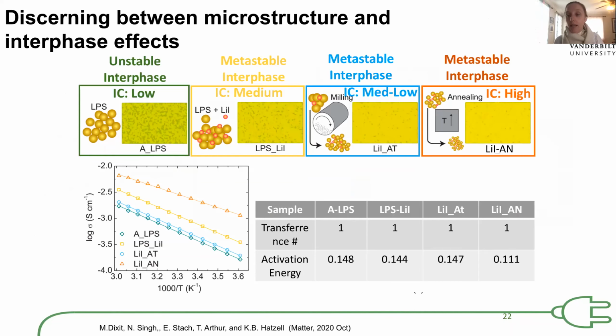We modified the interface by adding a halogen, lithium iodide. Our lithium thiophosphate that was amorphous is labeled ALPS. This is just the powders in their bare form, of course compressed and sintered. Then we have LPS with lithium iodide. Iodine is known to diffuse to the surface and reside in the interface, and lithium iodide is a conductor. Having the interface be ion conducting is good for having a metastable interface and also for decreasing the overpotential.